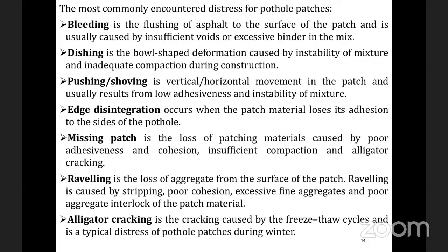So what is bleeding? Bleeding is nothing but flushing of asphalt. If excess binder is there, the binder will come up on the surface of the patch. So why does this happen? This happens due to insufficient voids and excessive binder. So next is dishing. Dishing is nothing but a bowl shaped deformation.